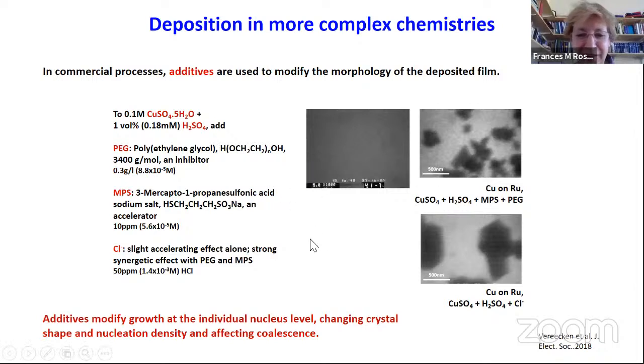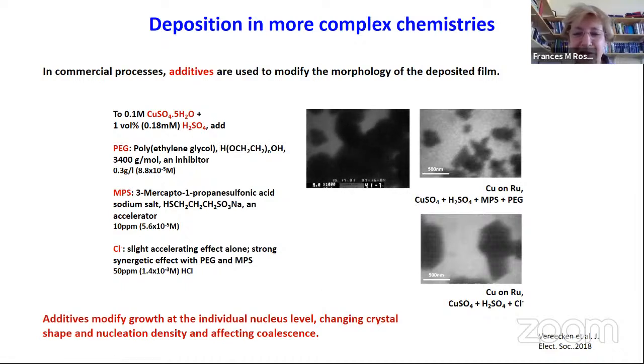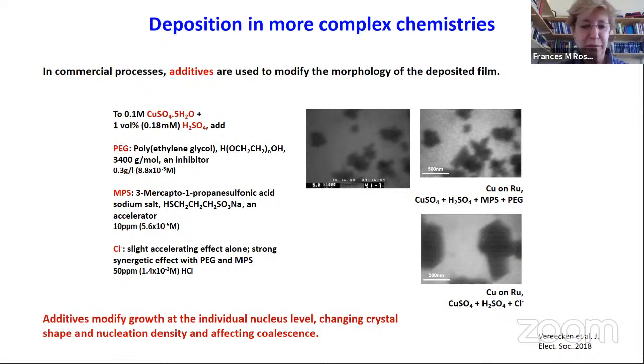and I want to show you another sort of ugly video. Do you see on this one, again, the resolution is not great, but you can see very clearly the shape of the objects is quite different from the ones I showed earlier. And here we're growing copper in an electrolyte that has some of the commercial additives that are used to control the growth when forming interconnects, and it's possible to evaluate the effect of each one of these things by observing in the microscope how it changes the growth morphology.